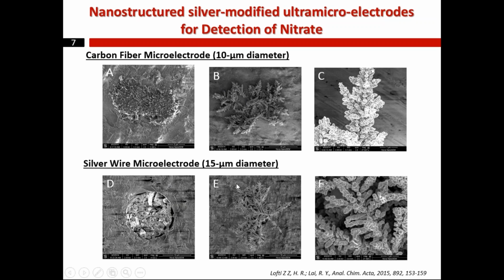Then pictures B, C, E, and F are showing the SEM images for the deposited silver on both carbon fiber and silver wire electrodes in 2 different magnifications. And as you can see, the deposited silver appears to have some type of nanostructure, and they have some type of dendritic growth.